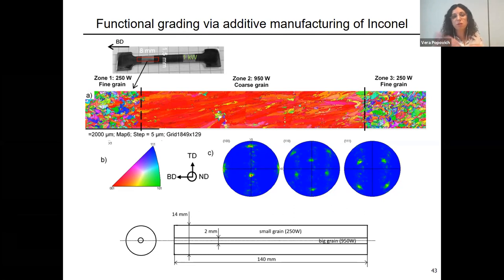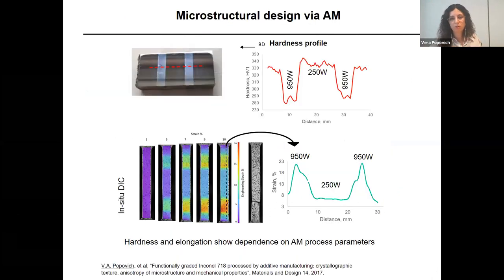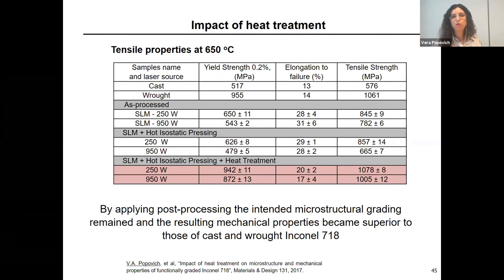While for creep, as we already discussed, you would like to have columnar or even single grains, and you would like to have this somehow in one envelope. So with additive manufacturing, my message is that you can get there, you can combine these two. But for sure, not everything is possible with just the as-processed condition, and this is an example that with additive manufacturing, you normally don't use it in the as-processed state.